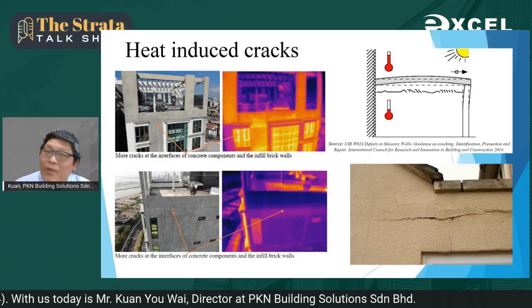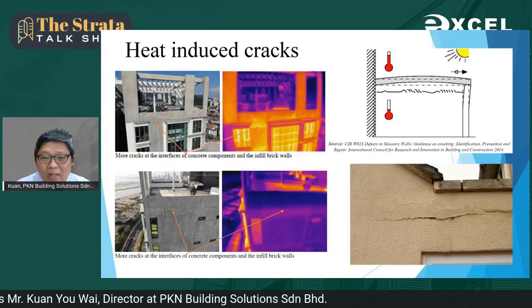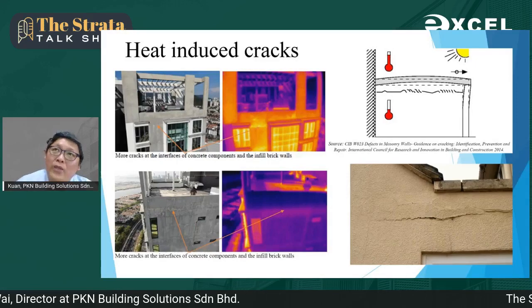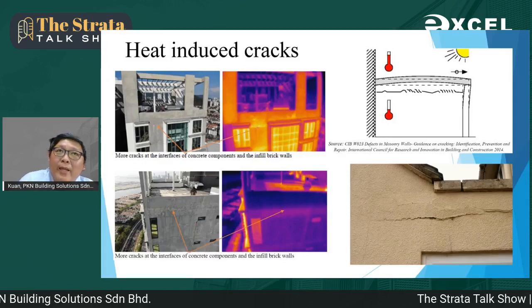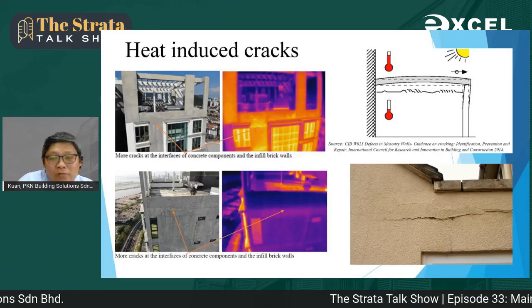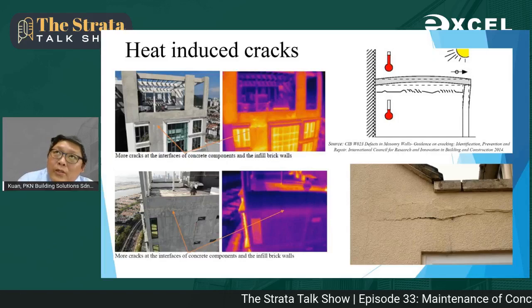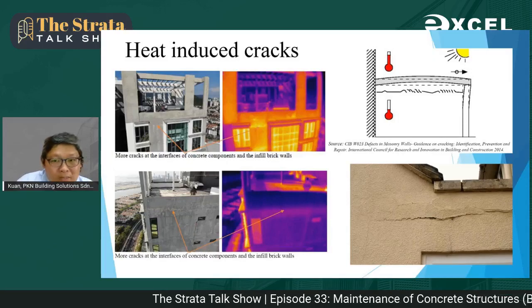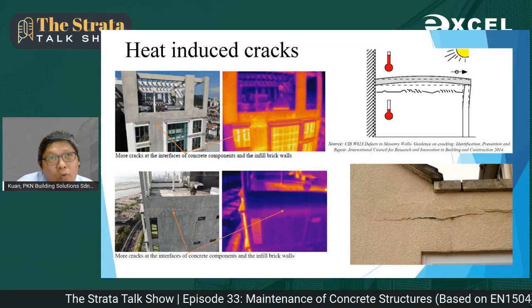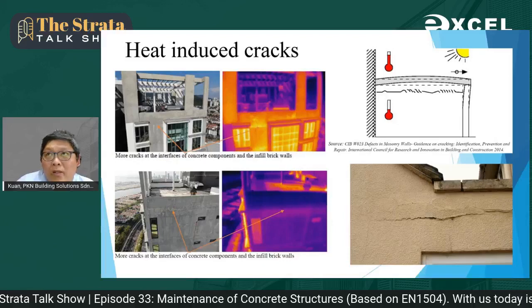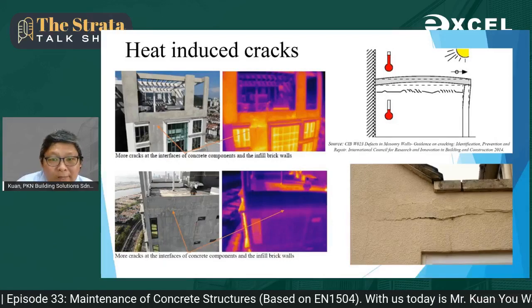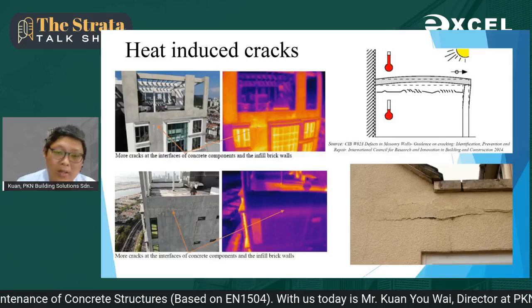From a primary study done in University Malaya under Dr. Zahiruddin, we know that at 1:30 p.m. the average heat on the flat roof reaches 82 degrees Celsius, and at 4 a.m. it can go down as low as 17 degrees Celsius overall in average.